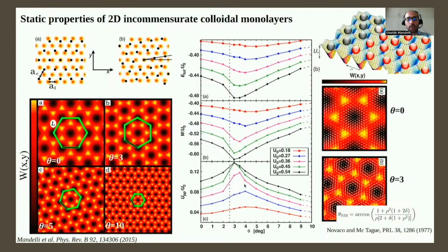Now, another thing that I would like to point your attention to is the following. If we follow the evolution of the interparticle potential energy and the substrate potential energy for increasing corrugation, we see that the interdigitation gets better and better. So the substrate potential energy gets lower and lower while the interparticle energy increases. This suggests that what is going on is that the colloids are trying to get away from the maxima, trying to get as close as possible to the local minima by exploiting these shear modes. And this is suggestive that a kind of Aubry transition is going on.